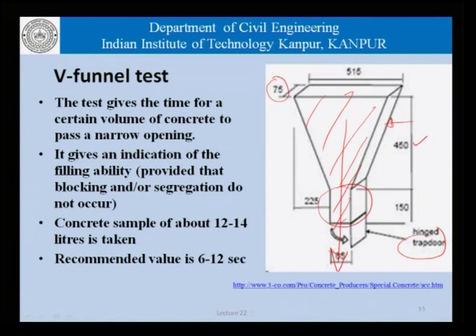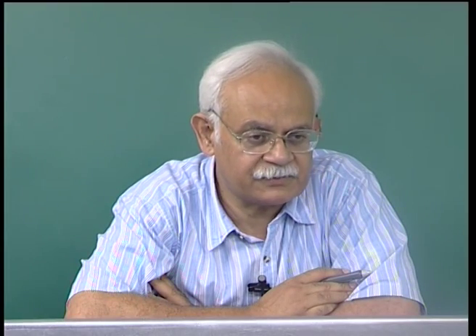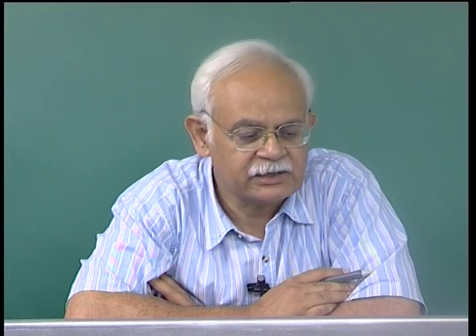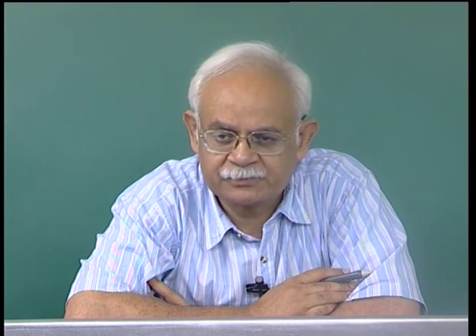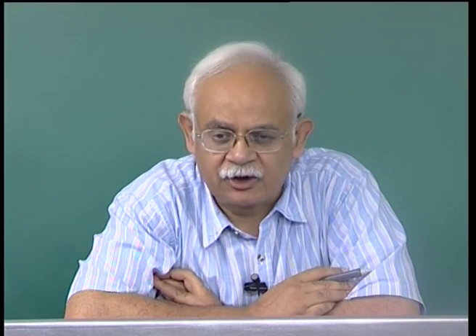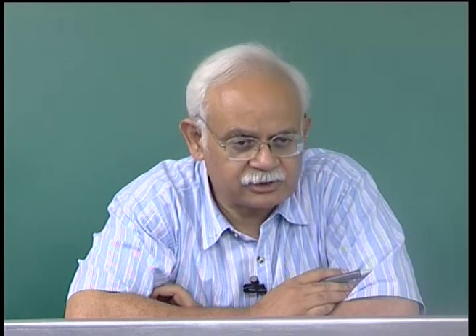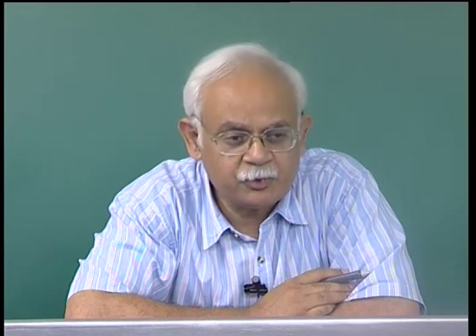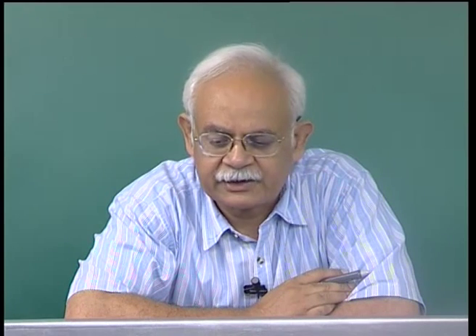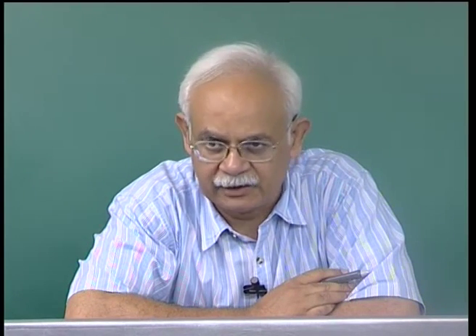Now, once the concrete is flowing from a larger cross sectional area to a smaller cross sectional area here, the possibilities of aggregate interlock can be easily checked. And that is something which the slump flow simply cannot do. The slump flow, therefore, is the measure of the unrestricted deformability, whereas a test such as the V funnel helps us evaluate the concrete from the point of view of aggregate interlock and so on. As far as the time is concerned, when do we say that all the concrete has actually passed through the funnel? One of the